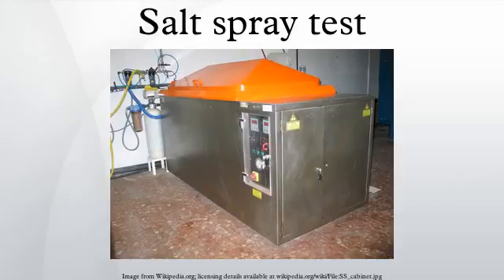Test specimens are placed in an enclosed chamber, and exposed to a changing climate that comprises the following 3-part repeating cycle: 0.75 hours exposure to a continuous indirect spray of salt water solution, prepared in accordance with the requirements of the test standard and acidified by the addition of acetic acid. This spray is set to fall out onto the specimens at a rate of 1.0 to 2.0 ml per 80 square centimetres per hour.